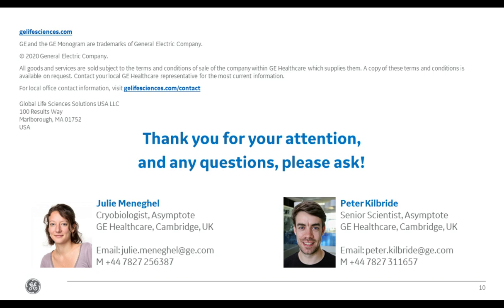So in general, having a lower viscosity on cooling tends to be better because it allows the cells to dehydrate more quickly, and it allows the ice to form more fully as well on cooling. So in general, a lower viscosity is better up until the point the glass condition occurs. However, it is cell-to-cell dependent. Some cells prefer glycerol or sugars compared to DMSO, and in that case, it's best just to optimize the cooling rates and then subsequently the warming rates for those cell types individually.